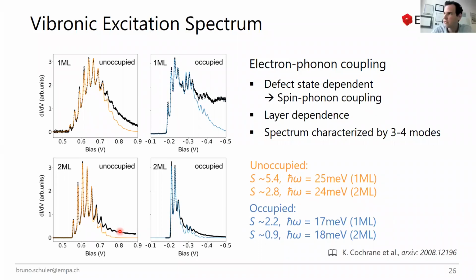We haven't tried this extensively with the helium ion bombarded one. What we have seen in the other sample, where we just anneal, is pretty much a stochastic distribution. So it was pretty random. There was not a line defect forming or something like this. I think in general, the mobility of defects is fairly low. There are covalent bonds and so on. At the end, we don't know, but since the distribution is stochastic in all the samples where we introduce these defects, I would expect a very low mobility of these defects.